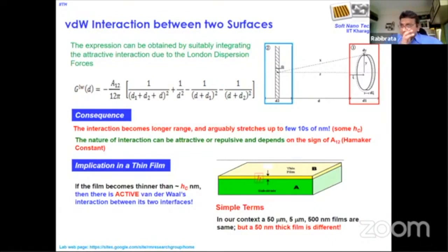There is physics behind it. Certainly, the coating is not what you want to have. The coating is there to provide some functionality. So you don't want to make this coating very, very thin. But then comes the question, how thin can you go? It turns out that there is a restriction on that, because of the so-called definition of the thin film that I'm going to present. In our context, a film is thin if there is an active van der Waals interaction between the two interfaces.